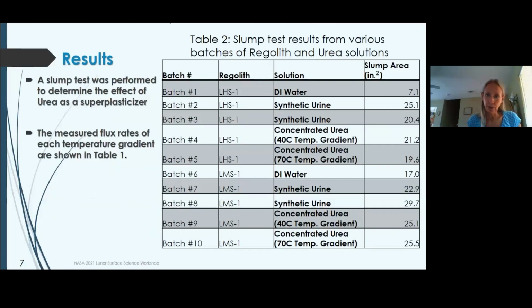Okay, and so these are the results from our workability test, our slump test. You can see that deionized water had a less of a slump area. In other words, if you just put DI water in the cement, it wasn't as workable as if you put in either the concentrated synthetic urine or the regular synthetic urine. They gave you more workability.